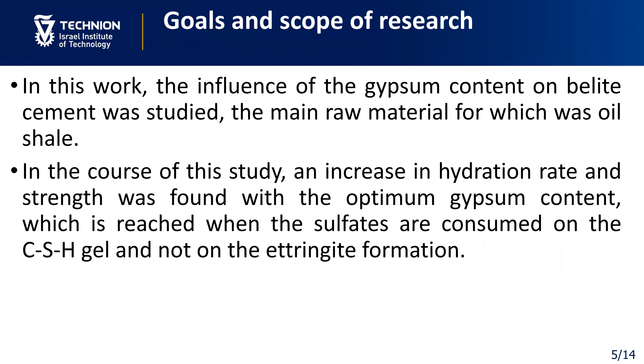In this work, the influence of gypsum content on belite cement was studied, the main raw material for which was oil shale. In the course of this study, an increase in hydration rate and strength was found with the optimum gypsum content, which is reached when the sulfates are consumed on the CSH and not on the ettringite formation.